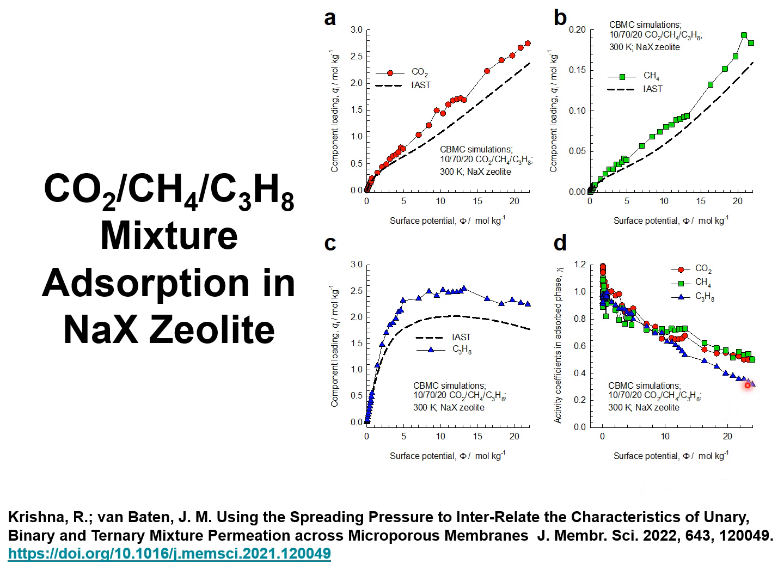We noted that as the surface potential tends to 0, all three activity coefficients tend to unity, and therefore, as I had previously mentioned, it is important to introduce a correction factor that correctly describes the influence of the surface potential on the activity coefficients. Recall that the surface potential is a proxy for the pore occupancy.